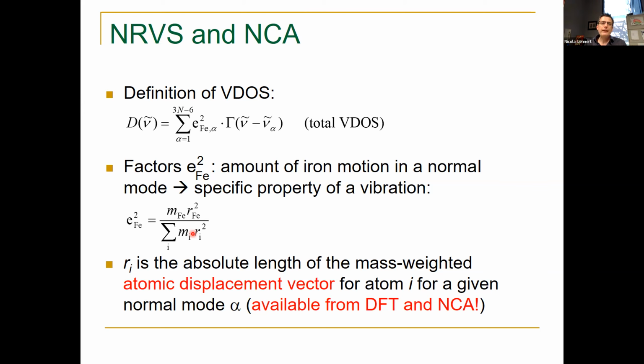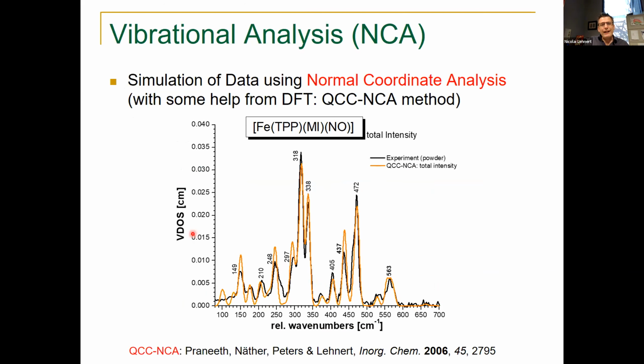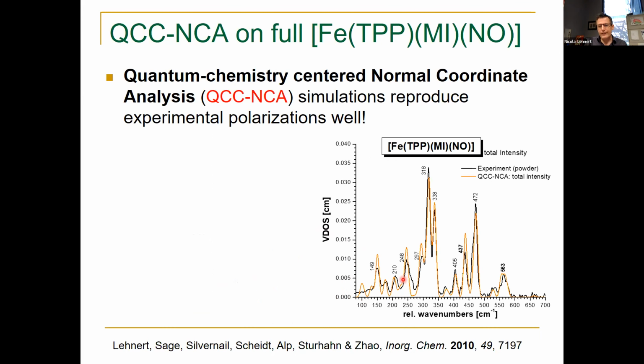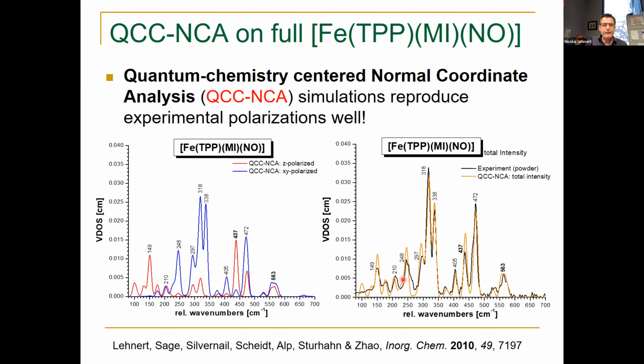And so that's another really big strength about NRVS, allowing us to do a much more rigorous analysis of the data, right? So going back now to this porphyrin complex, we then did what we call the QCC-NCA method, where we calculate a force field for the molecule of interest using DFT, and then we refine that force field using normal coordinate analysis. So it's kind of a combination of the two. DFT is not perfect, but we can refine then the calculated force constants in order to improve on that. So what you see here in black is the powder spectrum, and then in orange, that is the simulation of the spectrum that we were able to do. And we can also then compare in-plane and out-of-plane polarization in our simulation, which is shown here.